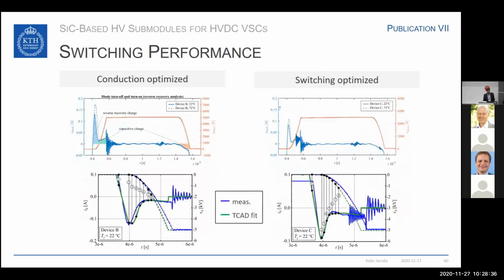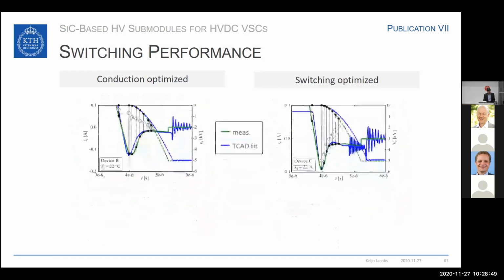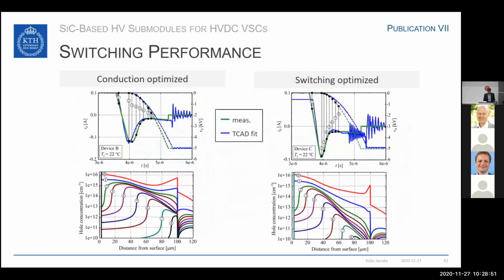We have then used these measurements in order to fit a TCAD model. And here in these lower graphs, you see the measurement in blue and the TCAD model in green. Different time instants here are marked with the numbers 1 to 8. It's a bit difficult to see because they're quite small, but the 1 is around here on the left side and the 8 is on the right side, and the same for the switching optimized device. And this enables us in simulation to see what happens inside of the device.